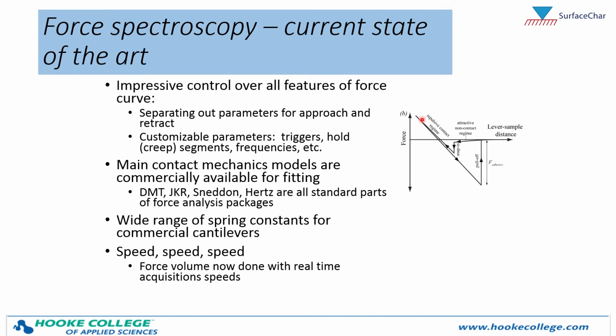We can have full control over the kinds of triggers. How far do we want to go in before we pull out? And the frequencies coming in and out. So an important side note on the frequency: when you want to do these force curve measurements, your frequencies of coming in, of poking, for viscoelastic samples, those frequencies matter. So if you're looking at a very viscoelastic sample like a polymer, you have to be a little careful about the frequency that you're poking at, because the ultimate modulus or stiffness that you measure will depend on that frequency.